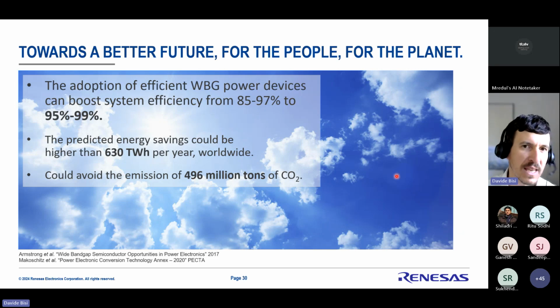And just want to give a few numbers. If we replace all the power converters using wide bandgap semiconductors like GaN and silicon carbide, the efficiency can go from 85 to 97% to 95 to 99%. So it can be a significant improvement in efficiency. And that means that each year we can actually save, according to the predictions, 630 terawatt hours of electricity. And just to give you a reference, this number is similar to the savings that LEDs brought to lighting.